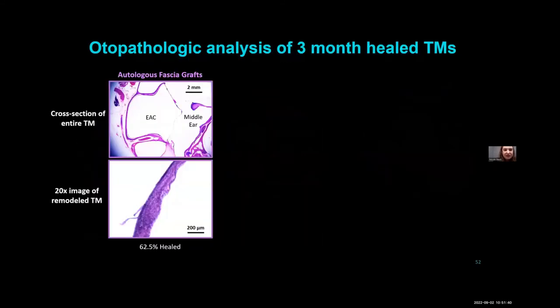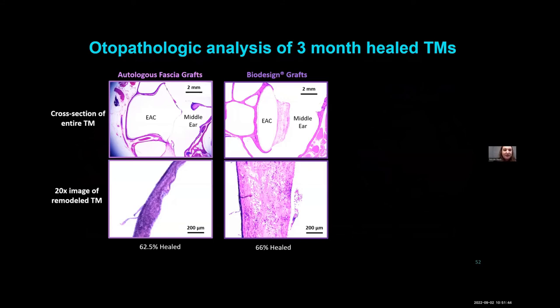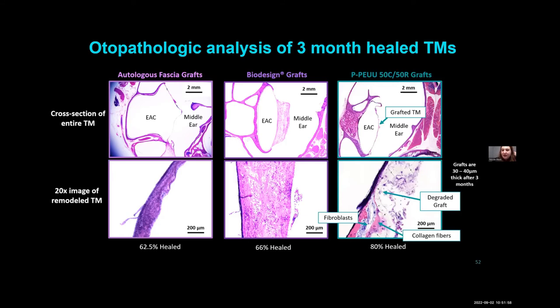And so looking at a cross-section histologically of fascia versus biodesign, again, you can see these both close the perforation, but you don't really see any sort of complex trilaminar structure reforming, especially that collagen layer. However, with the polyurethane grafts, you can see not only is the perforation healed, but the graft material has started degrading and integrating. It's about 30 to 40 microns thick after 3 months, so about a 60-70% degradation from its original thickness, as you see ingrowth of new collagen fibers and fibroblasts as well. And overall with these grafts, we were even able to see a higher healing rate. So 80% of the perforations treated with these grafts healed, versus only 62 and 66% for the control groups.